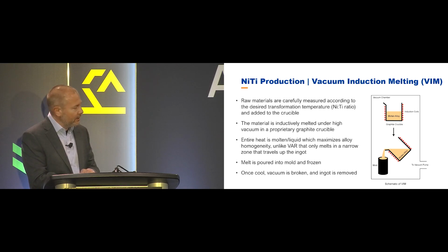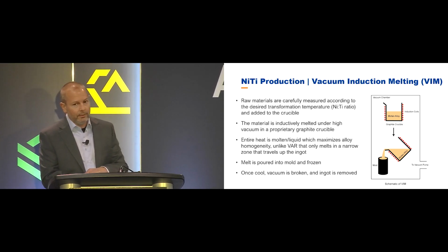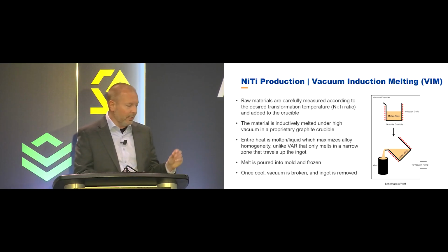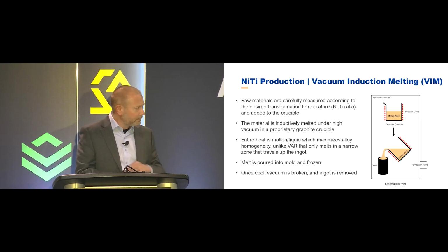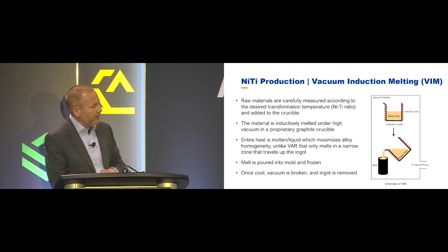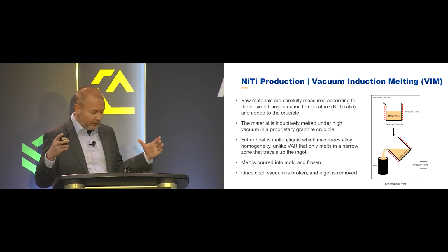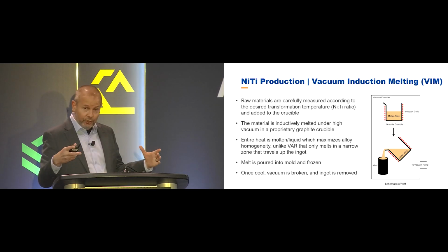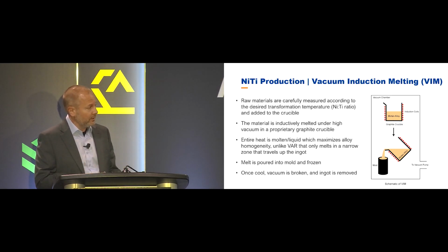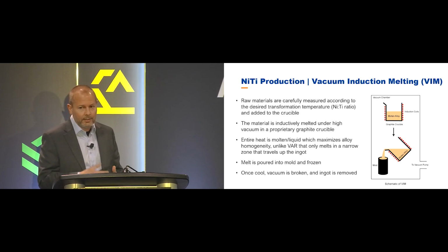So nitinol is very sensitive to the nickel titanium ratio. So we measure to essentially the last little piece of nickel shot. We measure out around a 200 kilogram charge, 420 pounds. All the materials go in a graphite crucible. The crucible was just a giant block of graphite that we have machined into a custom design for us. It lasts between 80 and 100 heats, and then we have to scrap it and put a new one in.